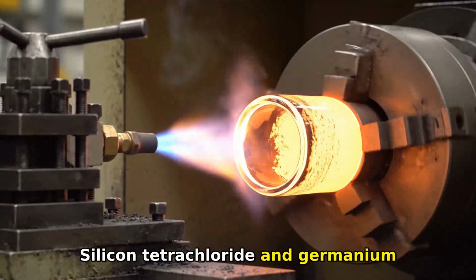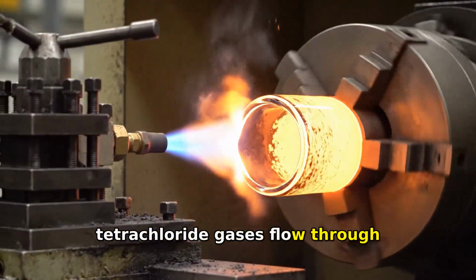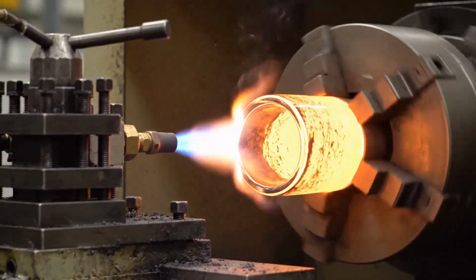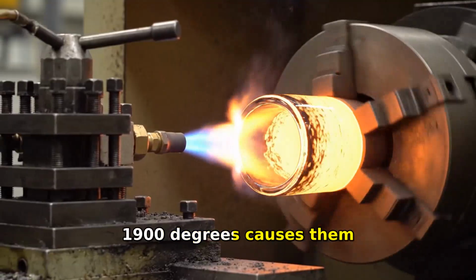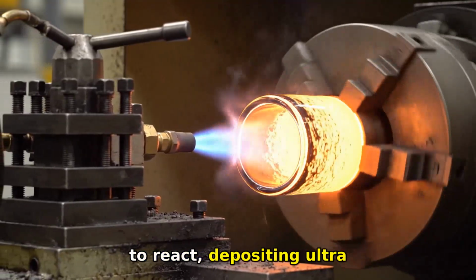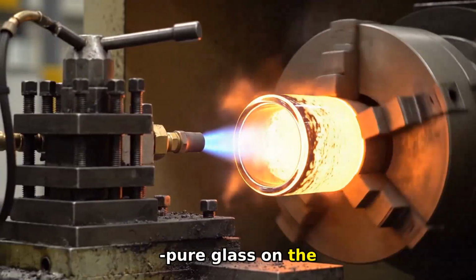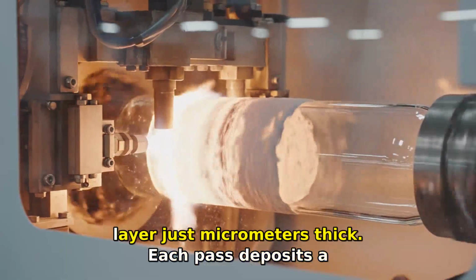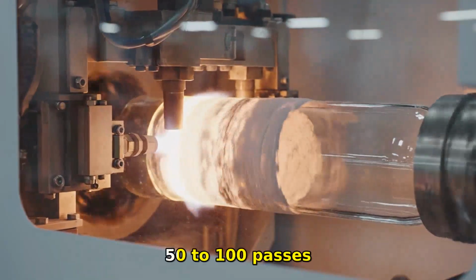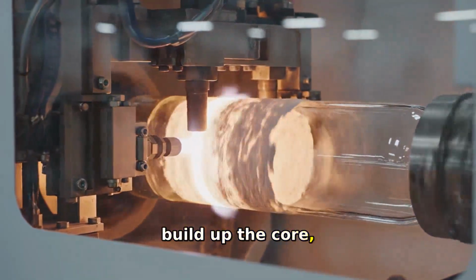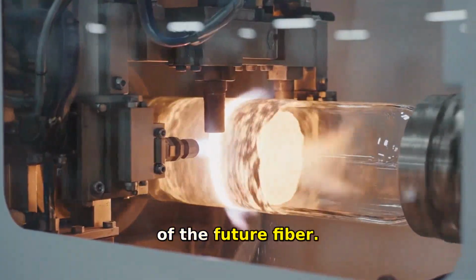Silicon tetrachloride and germanium tetrachloride gases flow through the rotating tube. The traversing burner at 1900 degrees causes them to react, depositing ultra-pure glass on the inner wall. Each pass deposits a layer just micrometers thick. 50 to 100 passes build up the core, the light-carrying heart of the future fiber.